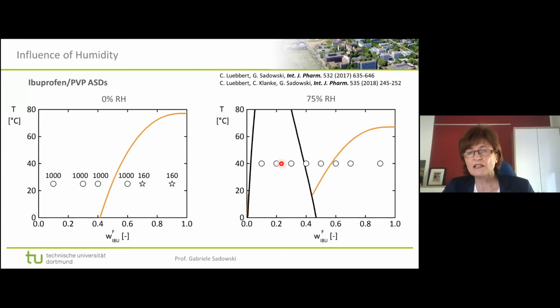But these three here on the left-hand side, they are right in the center of the miscibility gap. So we expected to find a demixing here. No crystals, but demixing. And the ones in the middle, particularly this one, but maybe also this one, this was what we expected not to crystallize nor to demix. So these two, these are the ones we expected to be stable. This is what the pharmacists want to have.